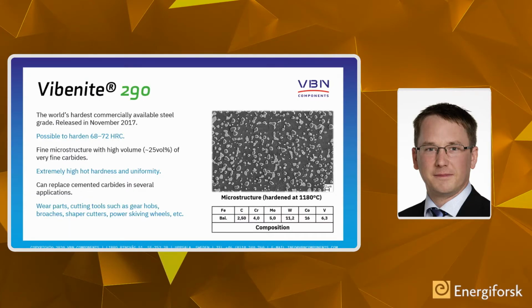Vibenite 290, this is the world's hardest commercially available steel grade. We have a hardening possibility up to 72 Rockwell. Also here we have fine microstructure and fine carbides, and we have a high hot hardness and very, very good wear resistance, of course, with this. So here you can use this in a number of wear applications. And typically, it could be cutting tools, gear hobs, broaches, etc. But also it could be any kind of wear-resistant needs. And the good thing is, of course, with additive manufacturing, you can process very difficult shapes to add into your existing components where you need wear resistance.